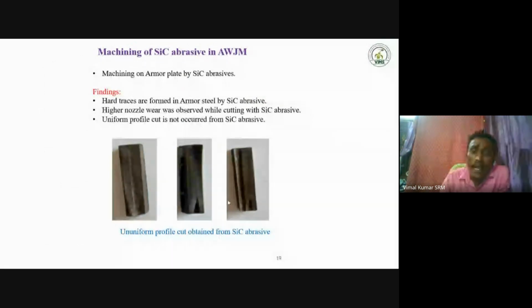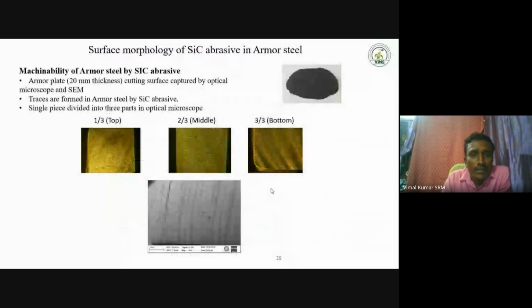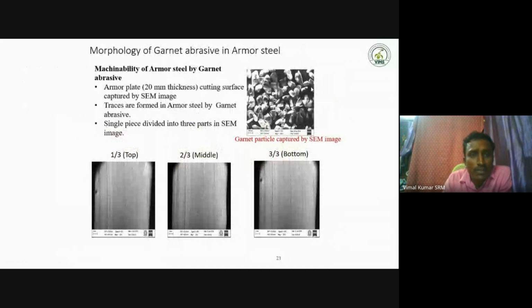High hardness in the sense it easily affects the surface of the material. So next we go for garnet abrasive. These are SEM images. See, some traces are easily identified when using silicon carbide. This is silicon carbide powder. It looks ash colored. So next we go for garnet abrasive. Garnet hardness is very low compared to silicon carbide, but the finishing is good. See, this is 500x magnification. Only a very small number of traces were identified, even at the maximum magnification. So for cutting armor grade steel with a water jet machine, garnet abrasive is very suitable, as we found in our research.